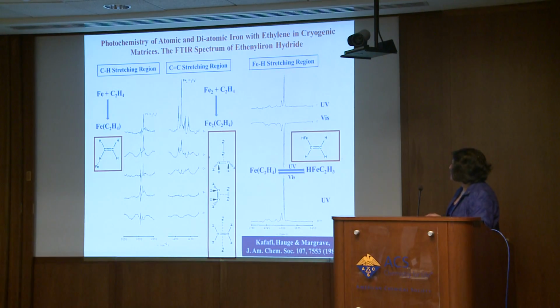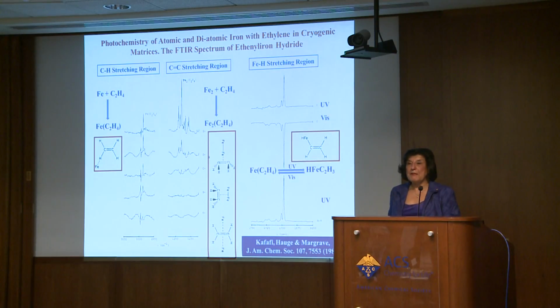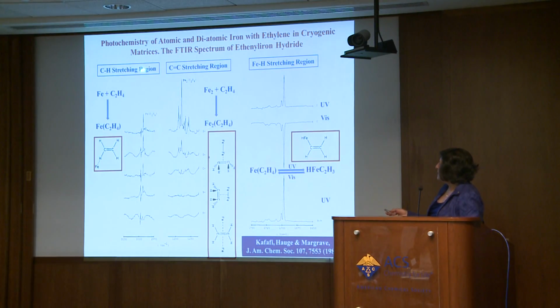Another reaction that I would like to share with you is a little bit more complicated, but it's related to the reaction of iron atom with ethylene. This is important in the chemical industry, where metals are used as catalysts for producing many chemical products. What we found that was intriguing, and I'll show you here different spectra in the CH stretching region and the carbon-carbon stretching region, is that the iron atom reacts differently with ethylene than di-iron, the two iron atoms together. Here we found that it forms a hydrogen bonded complex, which was a surprise.